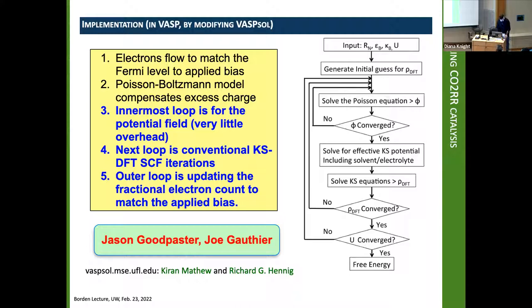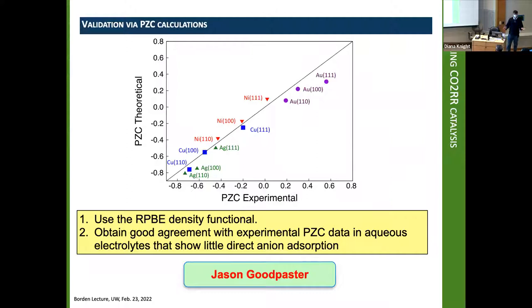Okay, so that's a little bit about the theory. Well, since I've told you how embarrassingly bad the theory is, I owe you a little bit of validation data. So this is validation data, and this is the potential of zero charge. How much bias do you have to apply to basically have a net charge zero at the solid-liquid interface? And you can see that the agreement produced by this RPBE with continuum solvent and applied bias with experiment for potentials of zero charge on the electron volt scale is actually quite encouraging.